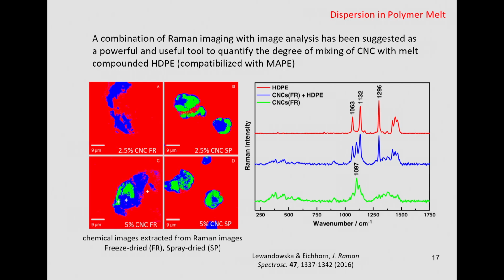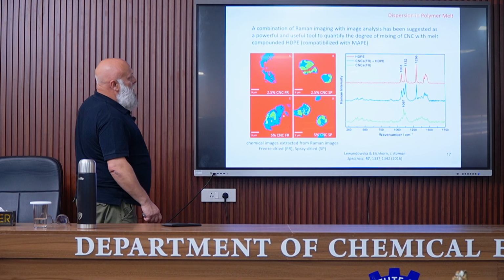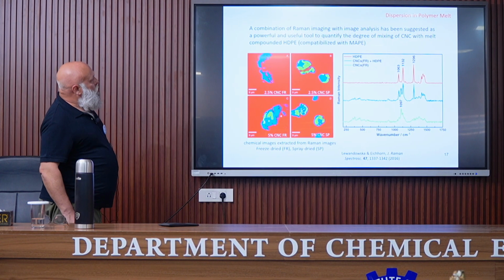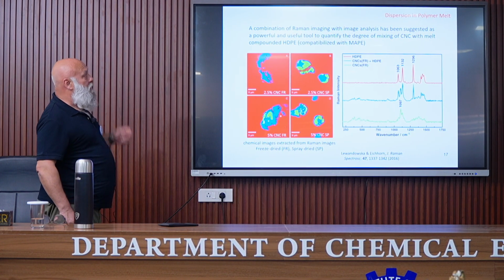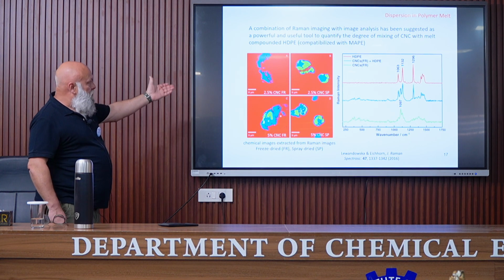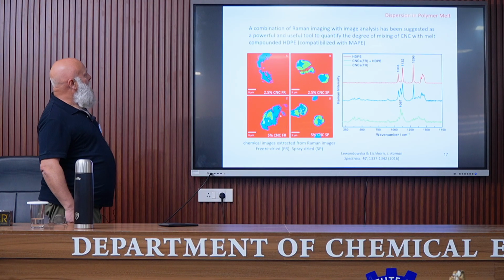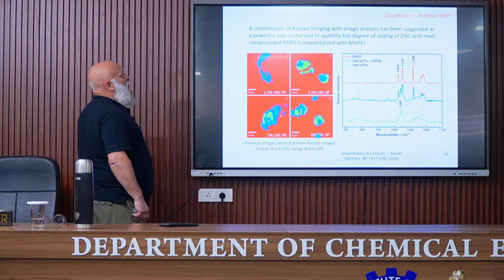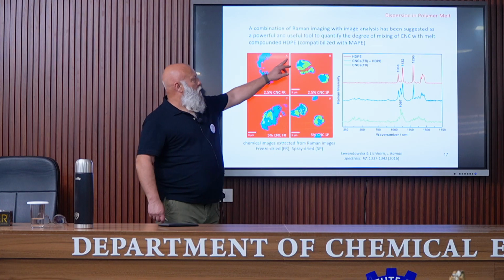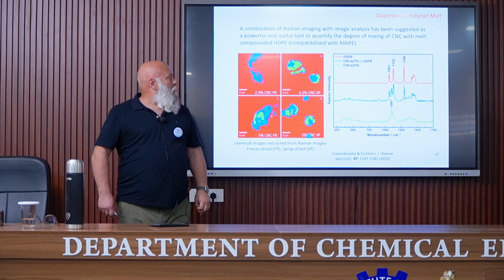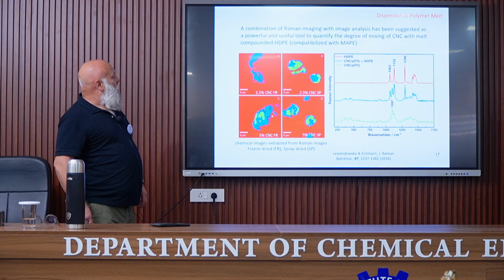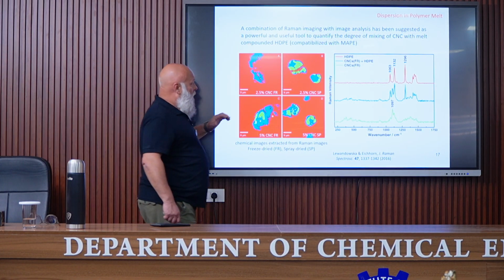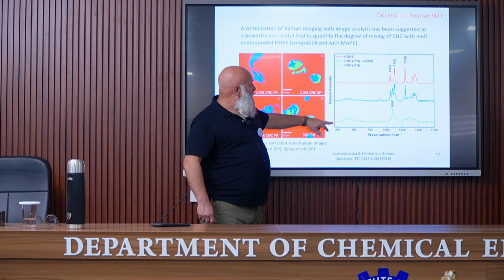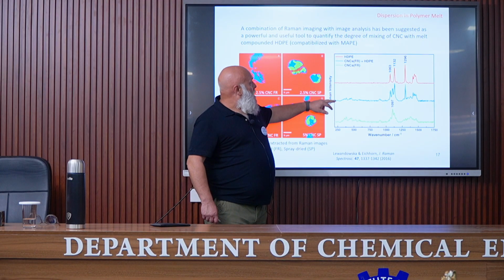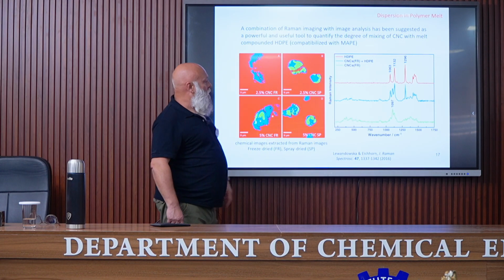He proposed a combination of Raman imaging with image analysis as a powerful and useful tool to quantify the degree of mixing of cellulose nanocrystals, in this case, with melt-compounded high-density polyethylene. A compatibilizer was used, a maleic anhydride polyethylene. And these are the Raman spectra for CNC, for high-density polyethylene, and for the mixture of these two polymers.